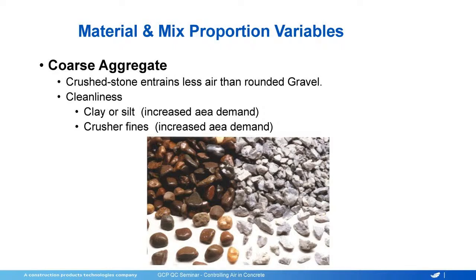Cleanliness. Again, the guy that's managing those stockpiles can pay attention, note any clay balls or any coatings on the aggregate as those are happening, and if you see a change, you're almost always going to see your air entrainment dosage increase because of those fine materials. And you likely will also see an increase in water demand, so you're going to get hit with a double whammy. So paying attention to those stockpiles, making sure that they're consistent in gradation and clean, is definitely going to make a big impact on your ability to control the air.